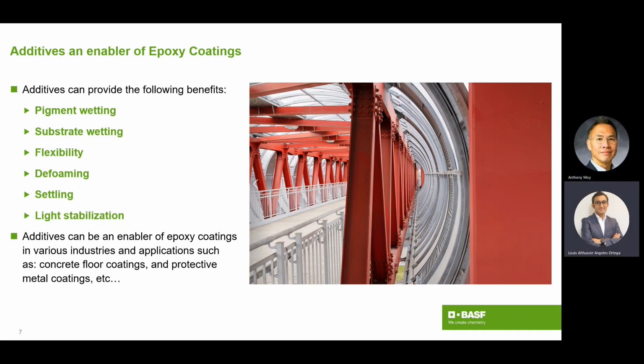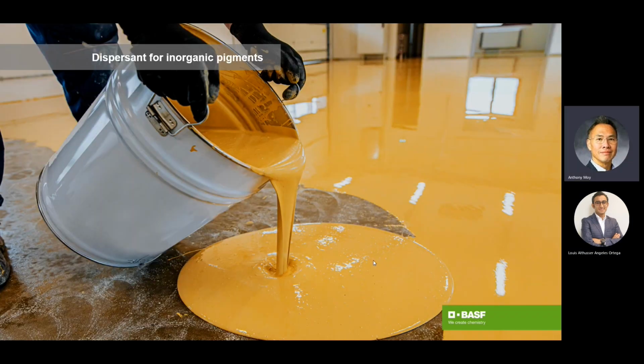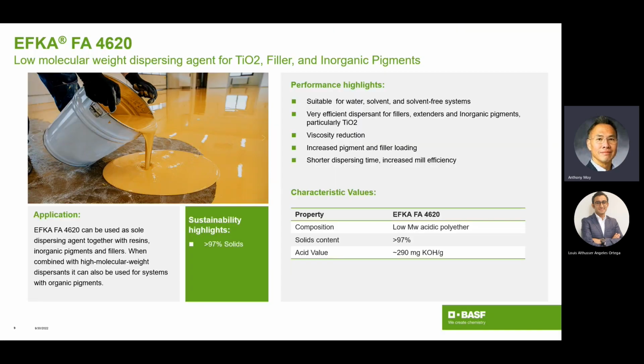According to your explanation, Tony, I would like to hear which additives you could use to incorporate pigments for aesthetics or protective effects. Yeah, so Luis, I would use a dispersing agent to incorporate pigments for aesthetic and protective effects. I would break that into two sections. One is for inorganic pigments. The dispersant that we would use for inorganic pigments would be EFKA FA 4620. As you can see in the graphic, it is a near 100% solids additive, so that means it brings in very little VOC. It's capable of use in water, solvent, and solvent-free systems. It's very efficient in dispersing fillers, extenders, and inorganic pigments, especially TiO2.